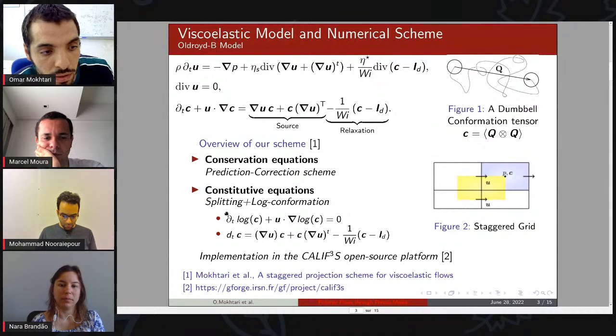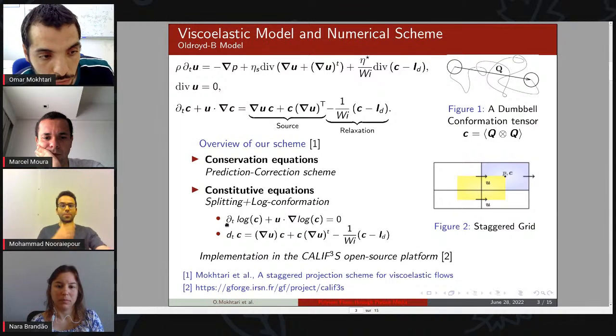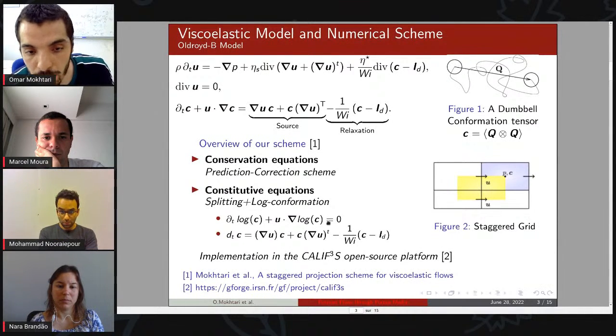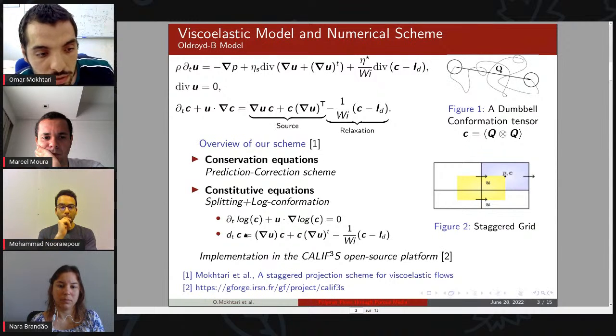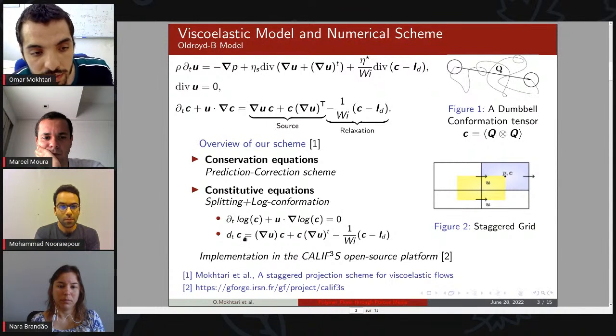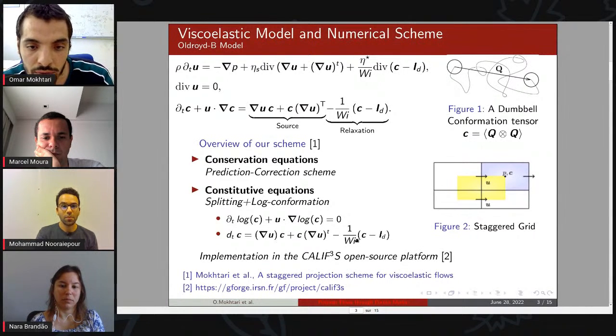So we propose to use splitting of this equation into two terms. The first equation is a pure advection equation on the logarithm of c, and the second one is a local ODE with a local time step depending on the local value of the velocity gradient.